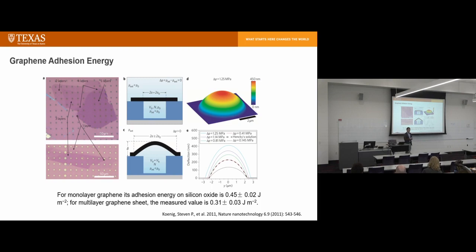So graphene adhesive energy is actually a pretty important characteristic, because a lot of people measure the graphene adhesive energy and the reported values are not consistent. A standard method is the blister method. This is some other people's work. They measured the graphene adhesion energy on silicon wafer, because silicon wafer is an important substrate. If you want to build microelectronics, they want to transfer graphene onto silicon wafer. So they measured the adhesive energy between graphene and silicon wafer.